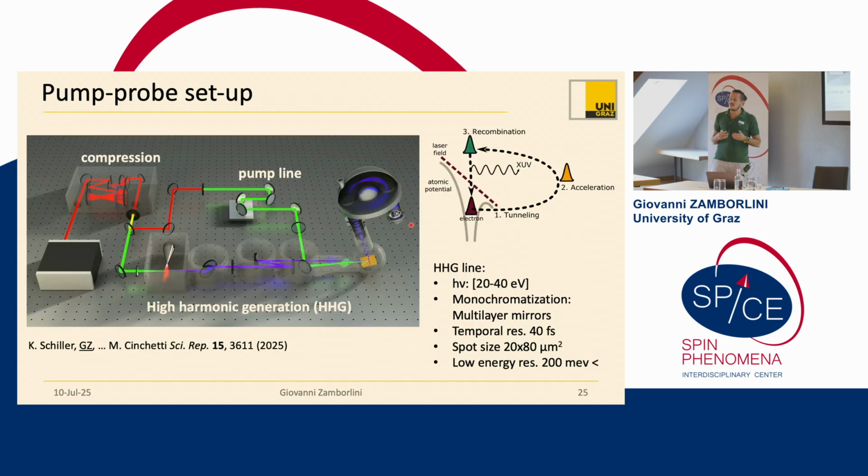The difficulty here is that, of course, we want to map band structure. In order to map band structure, you need to access high electron momenta. So if you're using pump and probe pulses which are visible, then the total momentum that your electron will have won't be that great, and you cannot map the entire Brillouin zone.